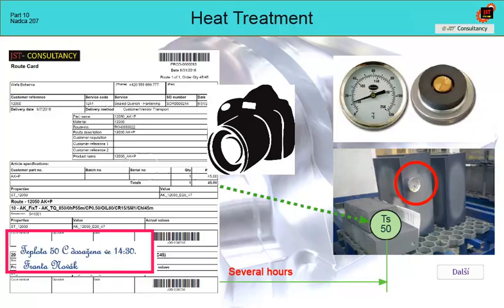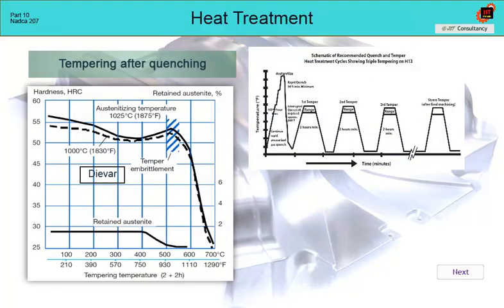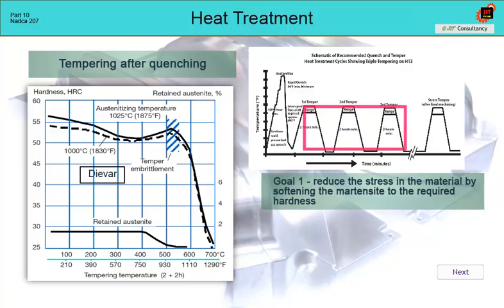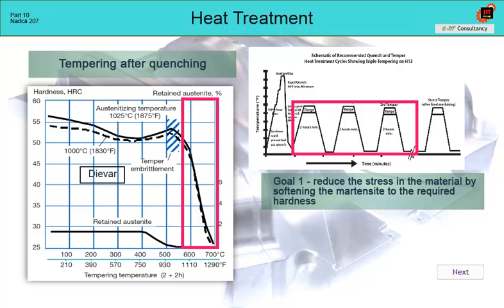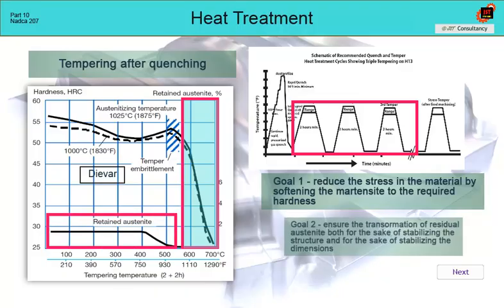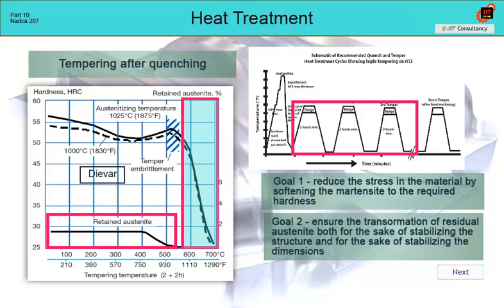However, it is already risky to cool the die below this temperature, as they could crack. Only when the inserts are properly cooled to a surface temperature of 50 degrees Celsius, we can start tempering. The tempering process has two basic goals. Reduce the stress in the material by softening the martensite to the required hardness, and ensure the minimal content of the residual austenite, for the reason of stabilizing the structure and stabilizing the dimensions. The brittle martensitic structure is thus transformed into a tempered martensite with corresponding hardness and impact toughness.